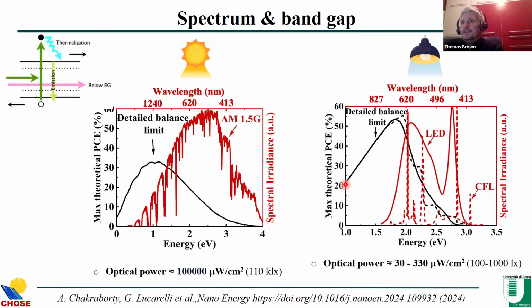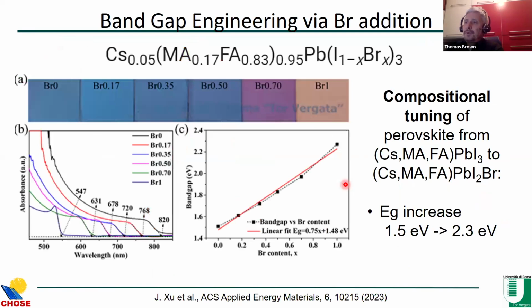So that's interface engineering. The other thing you can do is, as we've seen, increase the band gap, because you want to go towards 1.9 electron volts, which is the theoretical best for indoors. So via compositional engineering, you can change the band gap of perovskites. So you replace iodide with bromide. You can go from X equals 0, so fully iodide, to X equals 1, fully bromide. And you can see the absorption cutoff goes from 820 to 547 nanometers. So the band gap increases with bromide content going from 1.5 here to 2.3.